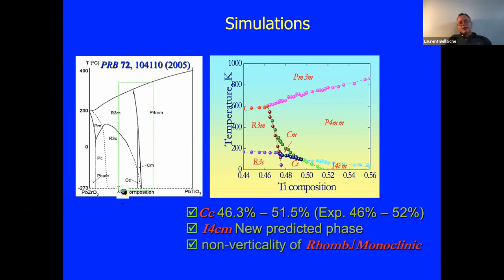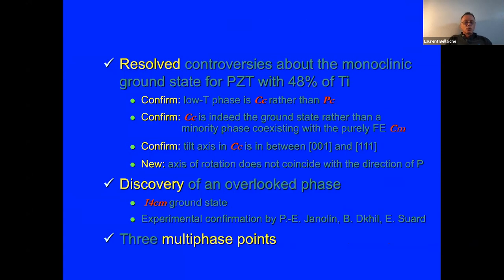We also found that technically, the region of separation between rhombohedral and monoclinic is not vertical. It's a little bit inclined. And you have very interesting points, which we call multiphase points, for which different phases meet each other in this temperature-composition phase diagram. So this was a summary of what we did.